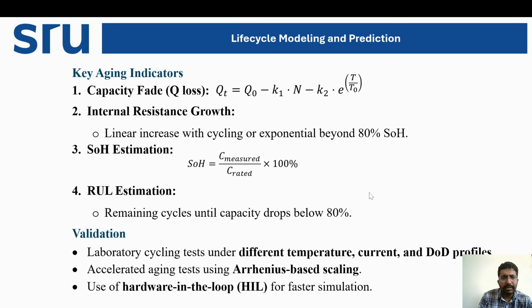Now coming to the key aging indicators. How will we know that the battery has aged? Some indicators should be there. Capacity fade is represented as Q(t) with respect to time. How much capacity is remaining? Q0 the initial condition, minus K1 into n, the number of charging discharging cycles, then K2 into exponential of temperature, the operational temperature. Then internal resistance growth: linear increase with cycle or exponential beyond 80% state of health.